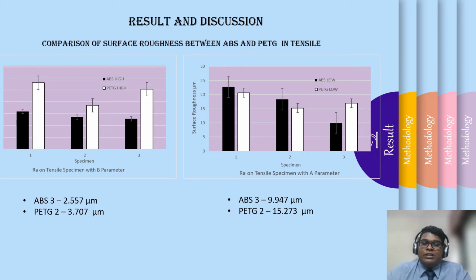Let's dive into the quality part. First and foremost, by comparing the surface roughness of ABS and PETG in tensile using the high level parameter, ABS has a smoother surface finish than PETG. This can be proven by the graph above. As you can see here, the black color indicates ABS while the white color indicates PETG. Using the low level parameter, PETG has a smoother surface finish compared to ABS.